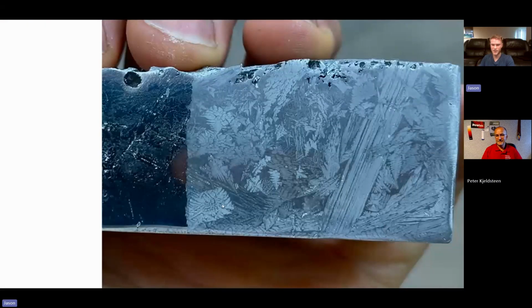So this is approximately 30% aluminum, and like you said, a lot of dendrites here. I mean, we see there's a big old rod here, but there's a lot of dendritic growth. And I have some ideas as to why this composition yielded more dendrites than others, but they're not fully fleshed out. I think it may have something to do with the amount of constitutional supercooling that's occurring as the intermetallic solidifies, having more versus less aluminum getting kicked out of the melt liquid, which can cause more or less stability in solidification. If we were to have less stability, we would be more likely to get dendrites. More stability, more likely to get these rods.